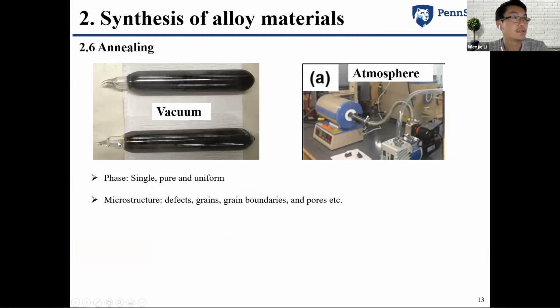So yeah, for most of the materials, in order to get more homogeneous compositions, we require post-annealing. We can either do it under vacuum, which is what I mentioned earlier, sealing it in quartz tubes, or do it under an inert atmosphere using the tube furnace to get a single, pure and uniform phase.